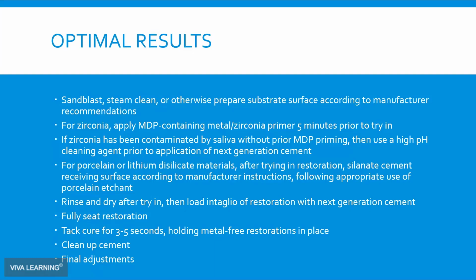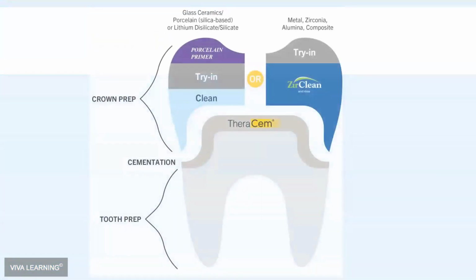After cleanup, depending how long the cleanup takes, if it takes more than a minute, which it hardly does, I'll cure it one more time for maybe 20 seconds. And then continue on to do my occlusal adjustments as necessary. So here's just a diagram of the general workflow in terms of what you're going to put where. In a porcelain or lithium disilicate situation, they left the etching part out of there, but you can etch it first. The porcelain primer is basically silane. You leave that on according to manufacturer's instructions, and then you proceed, try in, clean, rinsing and drying, etc.